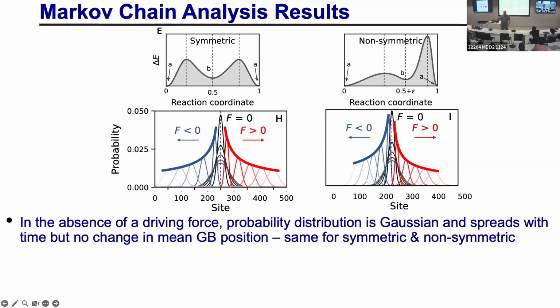Okay. So what I'm trying to show you here is that just making the energy landscape asymmetric is enough to show that the boundary migration rates in the two directions are different. Now, the other thing that's kind of interesting is if the force is 0, I don't tilt it, it's exactly the same. So this is only something for a moving boundary.